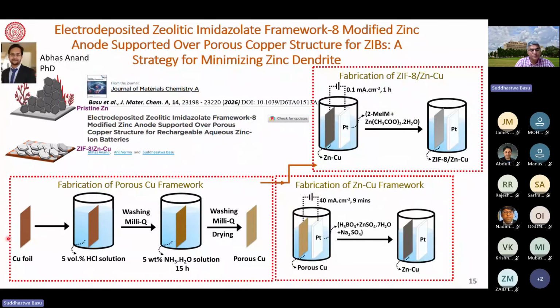So what we do, we take a copper foil and clean it with HCl as shown here, then we etch it with ammonia solution, and then we take a boron buffer. The buffer formulation is shown here, and you get a zinc deposition. So you have porous copper on which you have a zinc deposition. And finally, I take the methyl imidazole with zinc acetate, and we put it here. If we do the electrochemical deposition, we get the ZIF8 structure, or zeolitic imidazole framework structure, onto the surface, which doesn't allow as much bare surface for dendrite to grow.